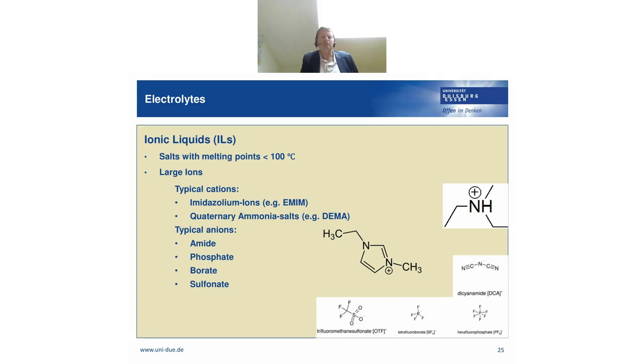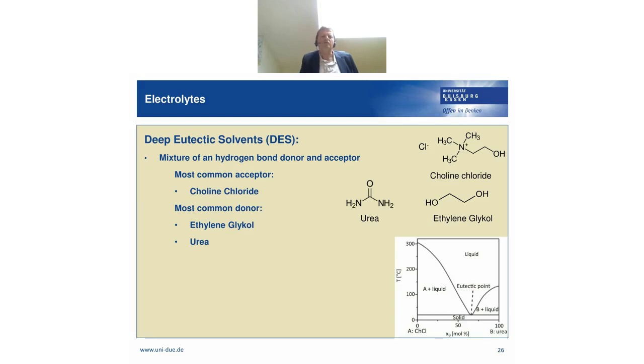into ionic liquids. We had the chance to get a funded project. Ionic liquids are salts with melting points well below 100 degrees. They are made up of large ions, typical cations and anions are displayed here. But even more interesting are the so-called deep eutectic solvents. We have a mixture of a hydrogen bond donor and an acceptor. Most common acceptor is choline chloride, depicted here on the right side. And most common donors are ethylene glycol and urea.